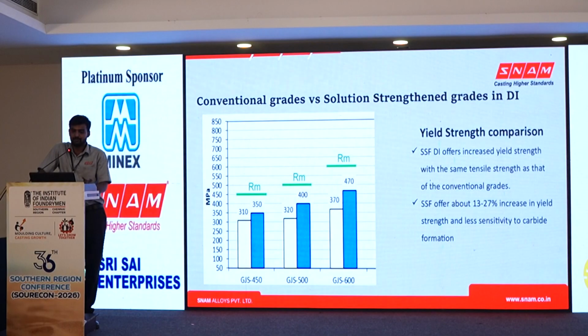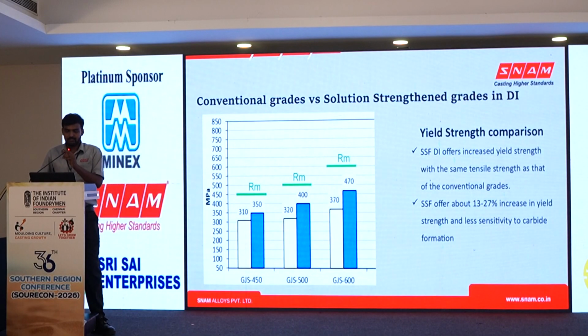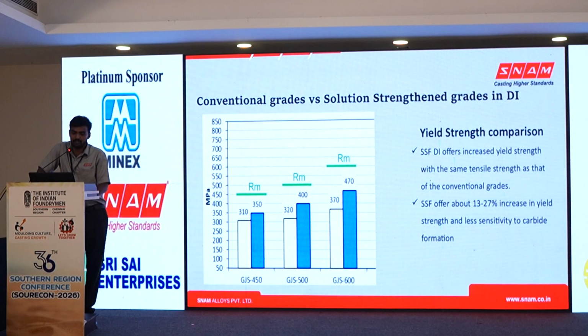So when we compare the same grades of conventional grades and SSF DI grades, as I told earlier, there will be increase in yield strength and elongation. So in this chart we can see comparison of yield strength for grades 450, 500 and 600. The yellow color identifies the conventional grades and blue color identifies the SSF DI. So we can see around 13 to 27% of increase in yield strength compared to conventional grades in SSF DI.